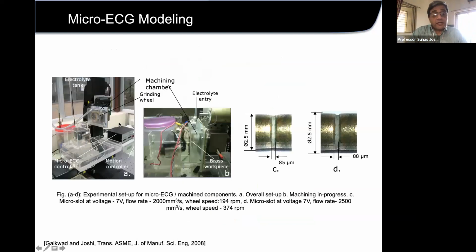So we ended up developing a small setup. This is a grinding wheel enclosed inside, and this is a workpiece which has a small part projecting out. You can see the grinding wheel here. There is a small rectangular cavity through which you can pass the work surface, and then the grinding will happen. Because this electrolyte is corrosive, you will find it very difficult to manage it. Otherwise, the whole thing will get corroded. So this is an interesting process where, using this, we could develop small grooves on the surfaces.